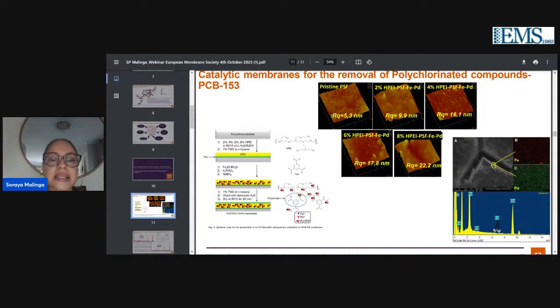We used different characterization techniques such as AFM and TEM before we actually embedded the iron palladium material, because membranes are quite difficult to investigate for the nanomaterial that's obviously within the thin film. So we looked at SEM-FIB. SEM-FIB has a beam that you can use to slice off the top of your membrane very slightly, without obviously destroying the membrane. So we could really see if the thin film consisted of the iron and palladium. And we did some EDS analysis. We could see that it is nicely spread within that area.